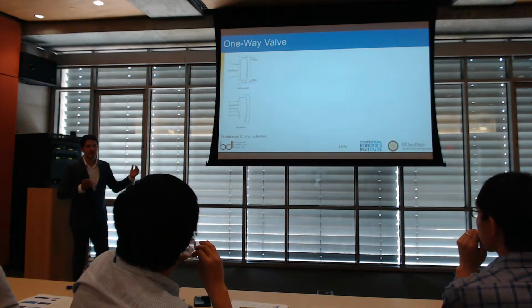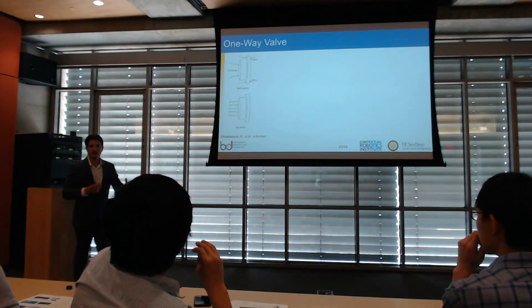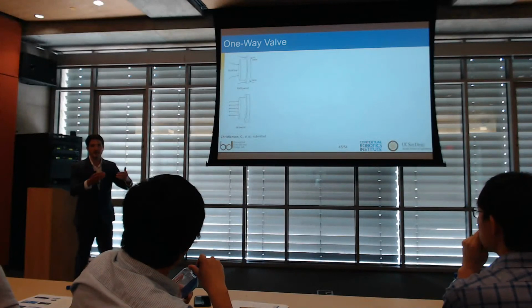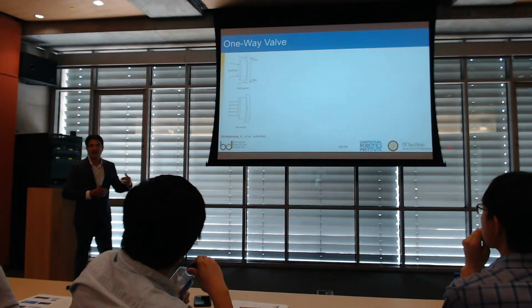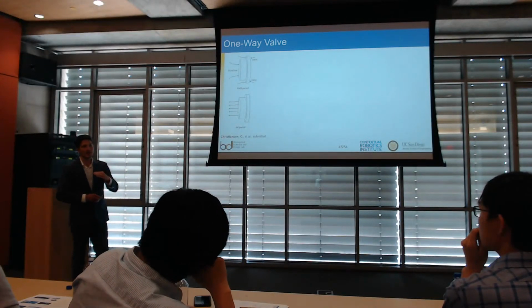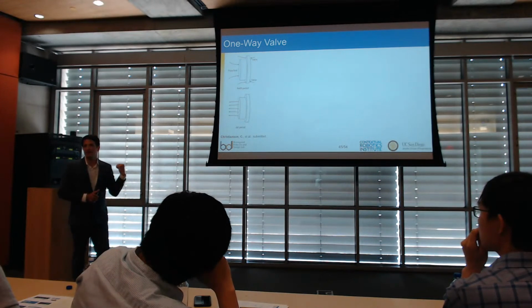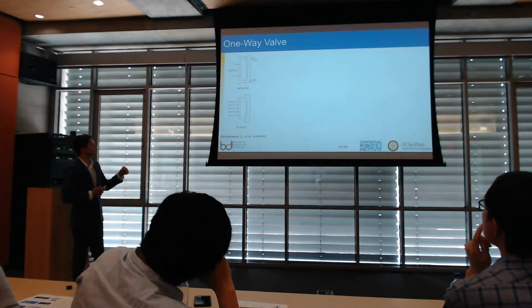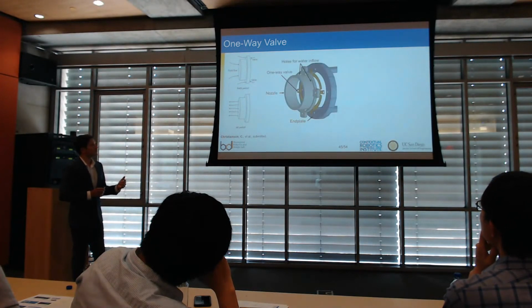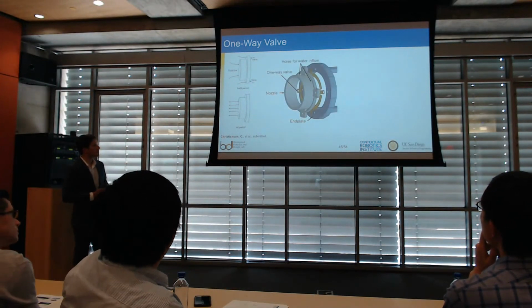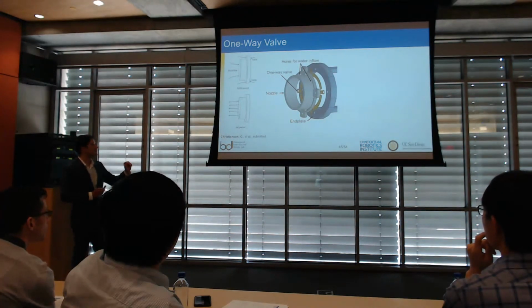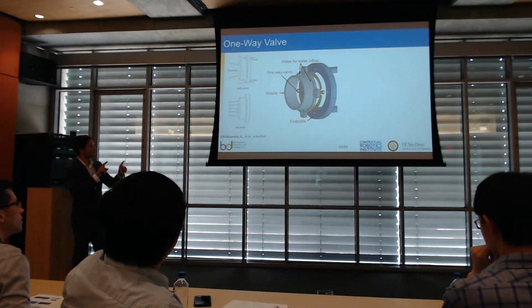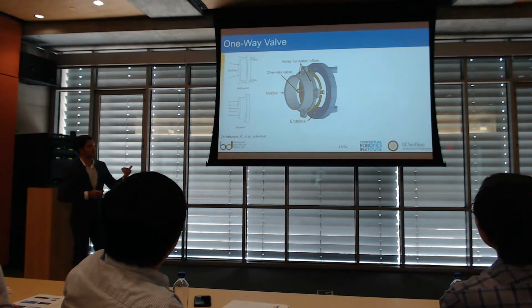And so we also want to look at valves. In squid, they have one-way valves where they can direct the flow to come in through one side and then out through the nozzle. It's more efficient than having fluid come in through the back end and then back out the same nozzle. So we want to look at if we can make nozzles to get more thrust. This is a CAD rendering of the design. It's a really simple design where we had small holes around the perimeter of the nozzle and a passive flap that controlled the direction. And we measured the thrust for this one.